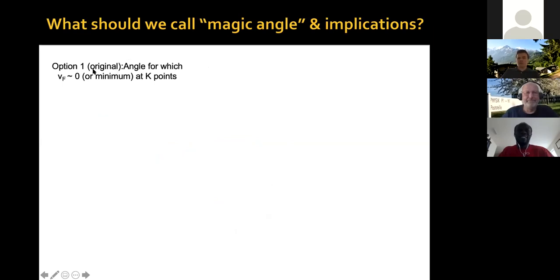Let's say we will call the magic angle the twist angle for which the Fermi velocity is 0 or minimum at the K points. As you rotate the twist angle, at the K points the velocity goes down, goes down, goes down. At some point it reaches 0 or its minimum. We call that the magic angle. Now, that's not the only possible definition.